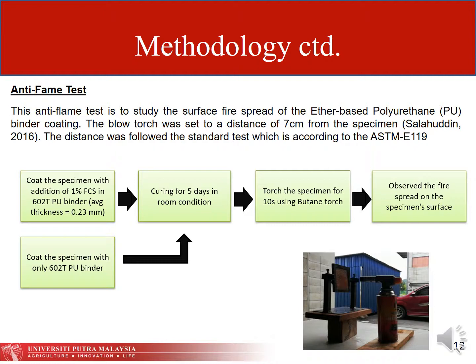The setup was the same as the fire test. First, coat the specimen with the addition of 1% fluorocarbon surfactant in 602T PU binder. The average thickness of the coating is around 0.23 mm. Cure it for 5 days in room condition, then torch the specimen for 10 seconds using a butane torch, then observe the fire spread on the specimen surface. Repeat using the same method, but the coating is without fluorocarbon.